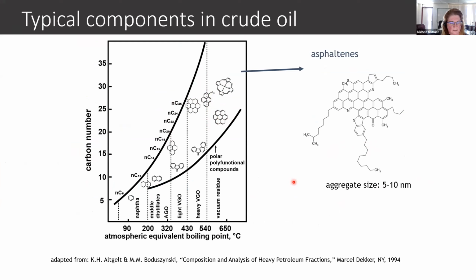And so basically what happens is this 12 to 18% fraction of every barrel is used in waste products, and it could also be burned for electricity. And that's just simply not an effective use of these hydrocarbons. And one of the reasons why it's very difficult to process these materials is because these aggregate sizes are about 5 to 10 nanometers in size. But I just mentioned that the zeolites that are often used in these refining processes have pore sizes that are less than 2 nanometers.